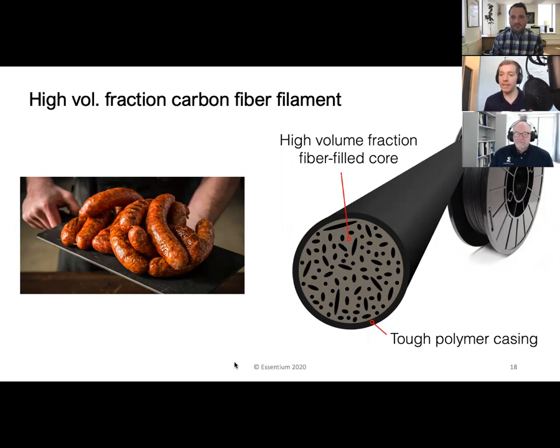So we do the exact same thing for filament. We put a thin, tough casing of the same polymer on the outside of the filament that encapsulates the highly loaded core. And this really opens up an entire new possibility for composite materials. And again, I'll say the HSE is uniquely suited to print with these kind of materials.